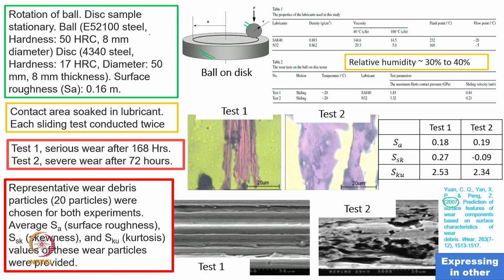They try to keep the ball as 52100 steel, with very high hardness, in this case 50 HRC, while 8 mm is the diameter of the ball. While for the disc they kept a relatively soft surface: 4340 steel is a medium carbon steel, and its hardness is smaller, maybe 1/3 compared to the ball. The diameter is bigger, while thickness is kept the same, also 8 mm.